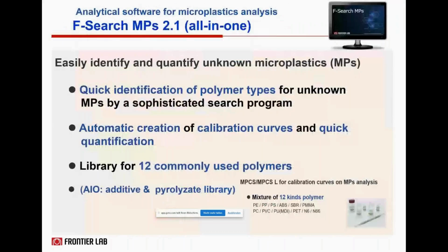Finally, we have a database and search software system for microplastic identification and quantification called F-Search MPs, actual version 2.1. The features are the quick identification of polymers or polymer types for unknown microplastics by a sophisticated search program, automated creation of a calibration curve, and quick quantification, really in less than 1 minute. It's a very fast algorithm. And the software comes with a library for the 12 commonly used and most abundant polymers that we unfortunately find in our environment. And the all-in-one version also contains other additives and pyrolysates, so you can also identify, but not quantify, other additives and other polymers which might be in your chromatogram.